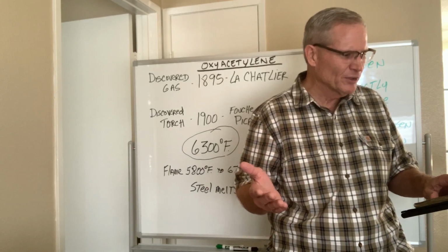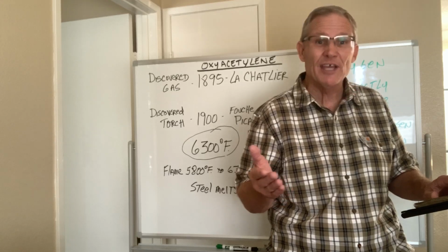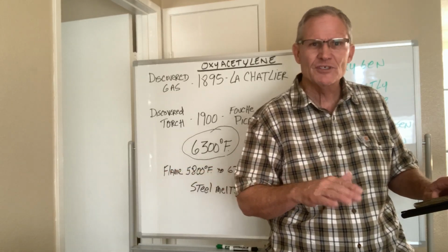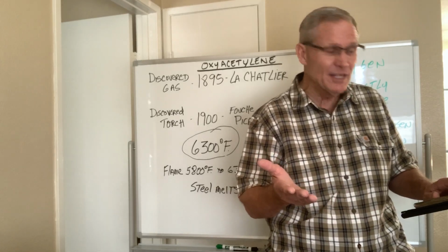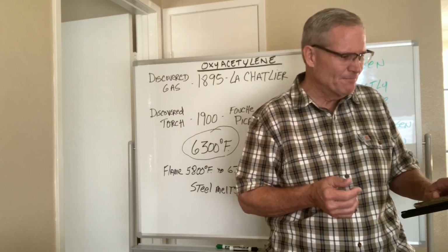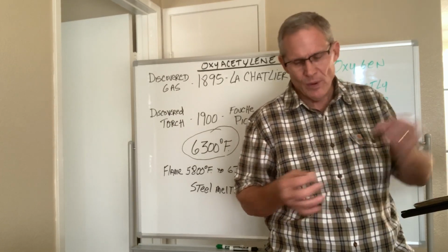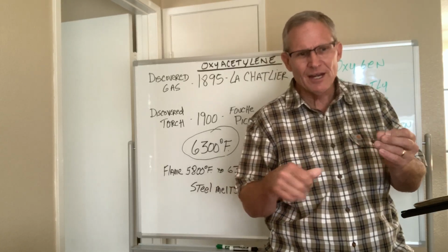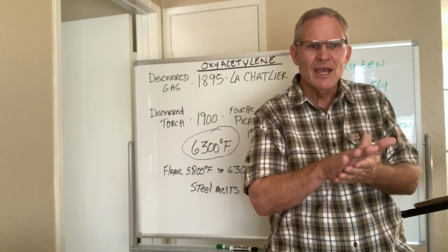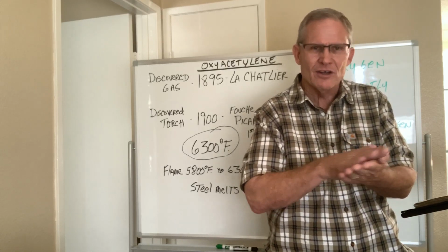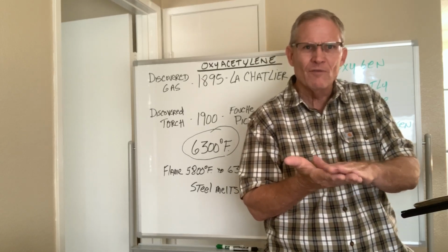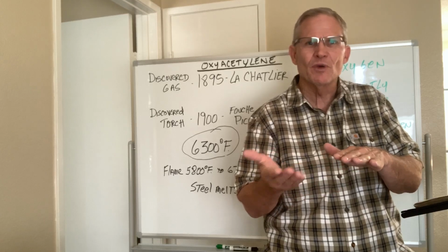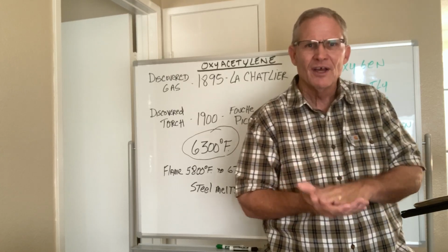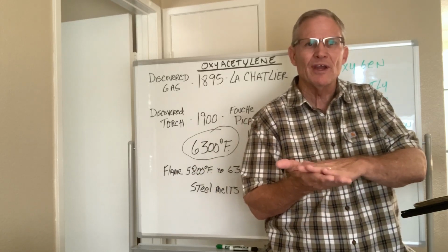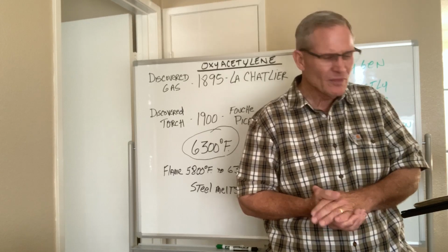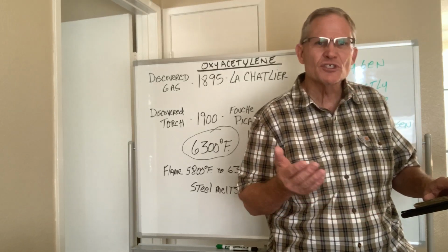Now, besides welding, oxyacetylene is also used for case hardening, where we're trying to put a hardened surface onto a piece of metal where it might have some wearability, where they use Hastelloy and tungsten carbide. We actually have tungsten carbide filler rod where you would heat it up and put layers of tungsten carbide on metal where you have a lot of wear on a surface, maybe on a backhoe bucket, something that's going to be worn for a while. It helps with the wearability of the bucket blade itself, where you're not having to change the blade, but you're just wearing out the hard surfacing material on it. But it's used for that, and also stress relieving.